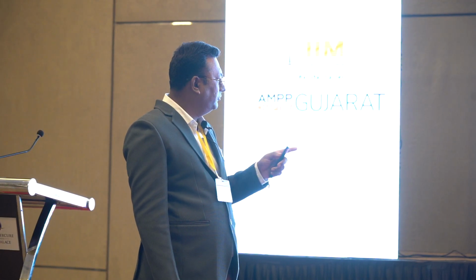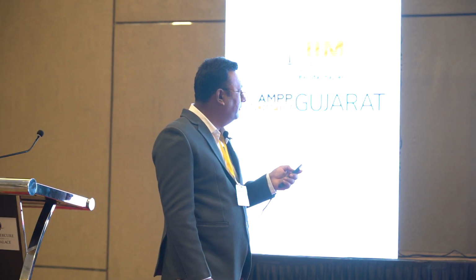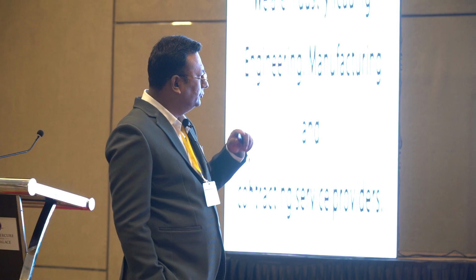This gives one data set where you can see the behavior. This is again my research data. You can see we found two values, one for L grade and one for LMP grade. We developed 309 L graded weld overlays on low alloy steels, in L grade and LMP grade. You can see the data for the LMP.